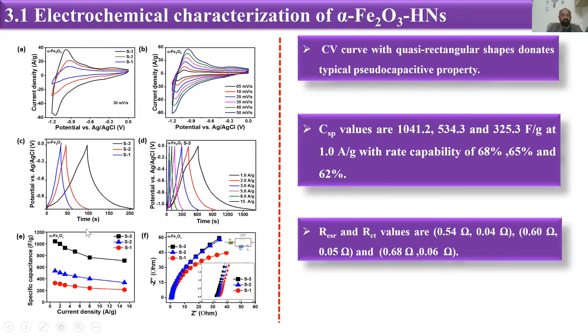Also, we have calculated the specific capacitance of our sample, which was different for different scan rates; the maximum is about 1040, 530 and 325 at the rate of 1 A/g. And we have EIS, electrochemical impedance spectroscopy, and we calculated our ESR and RCT values, which were quite low, and which shows that our materials have shown good electrical properties.